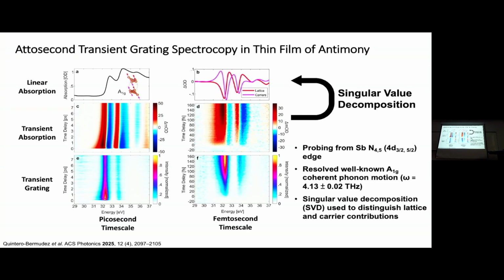So now, if you look at the maps, like this is a transient absorption experiment here, and you see it's rather complicated. You have a lot of things to deal with. If you do the transient grating, it's so simplified. Like it's suddenly really clear that there's a coherent phonon motion here, and then we can pick that out. You can take this signal and do a lot of work with like singular value decomposition. So everybody's computing and doing all kinds of manipulations on this data to try to find out what is underlying this and pulling out different pieces and so on. Or you could do the transient grating and vastly simplify the result. This is the point that I want to make. So rather than doing the hard work, you can get something kind of rather more easily, perhaps, in what you're going to find out.